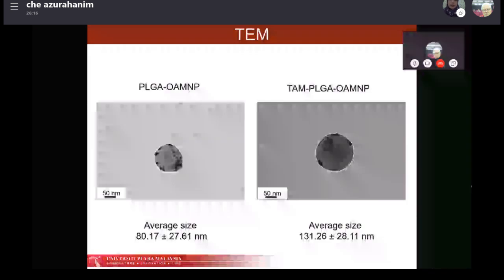We can see that when we just have PLGA OA-MNP, the size is about 80.17 nanometers, and after we add tamoxifen, the anti-cancer drug, the size increased from 80 to about 131.26 nanometers.